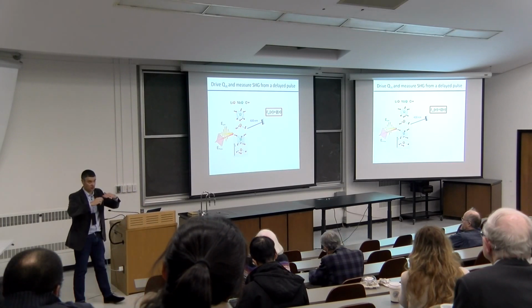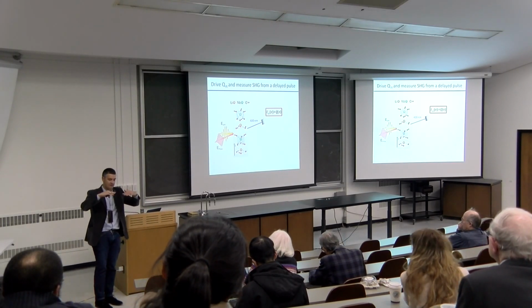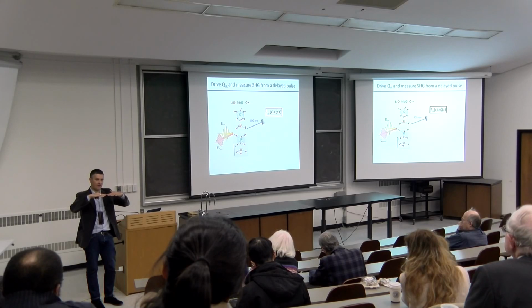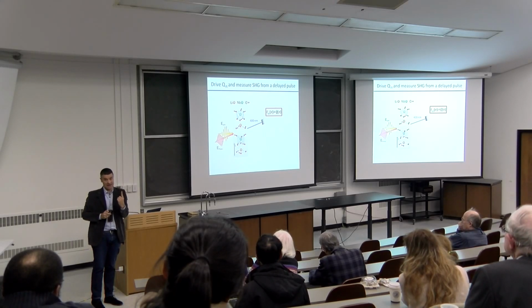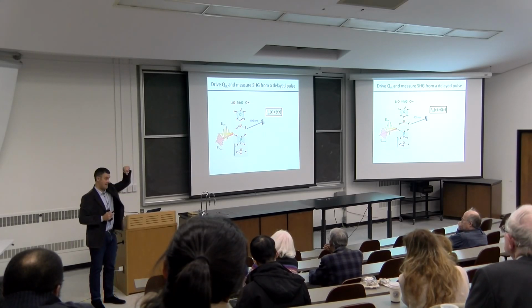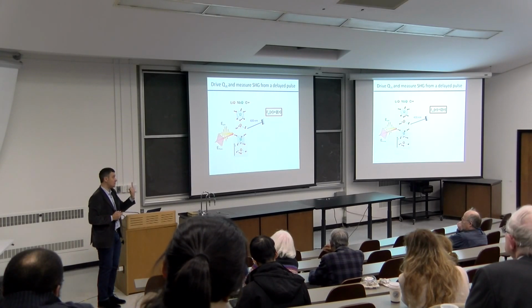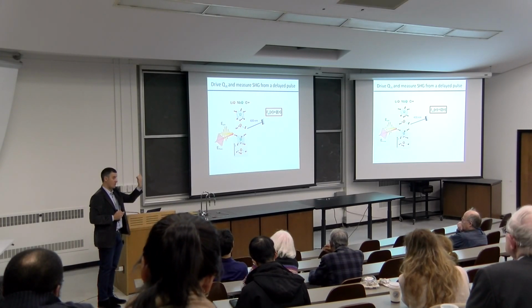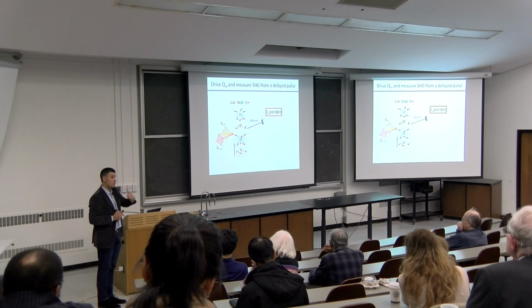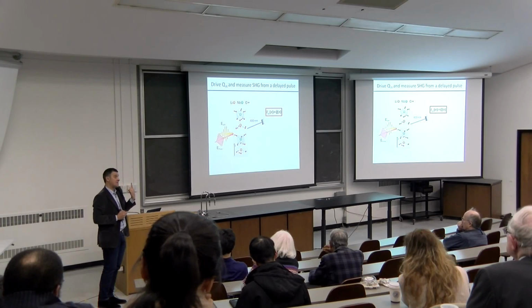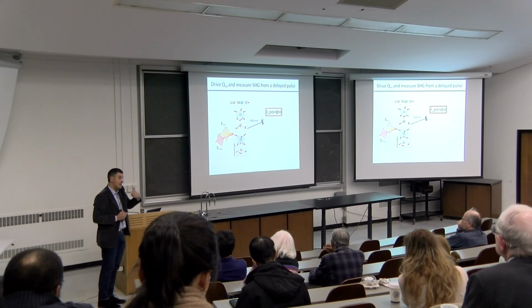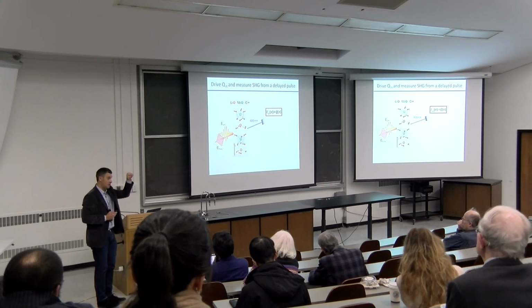So imagine now to have an odd mode. Take a system that respects inversion, that is not a ferroelectric. And now I drive an infrared active mode up and down. What this is going to do is break inversion up and down at twice the frequency of the phonon, which means that I will get a second harmonic that gets larger and smaller and changes phase